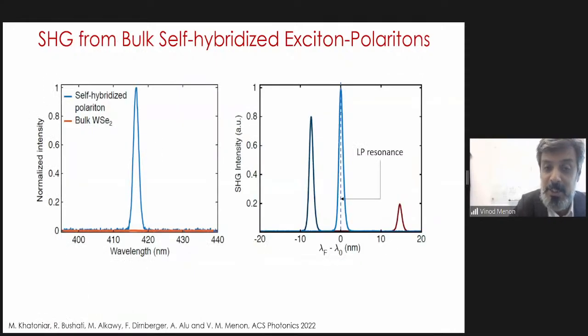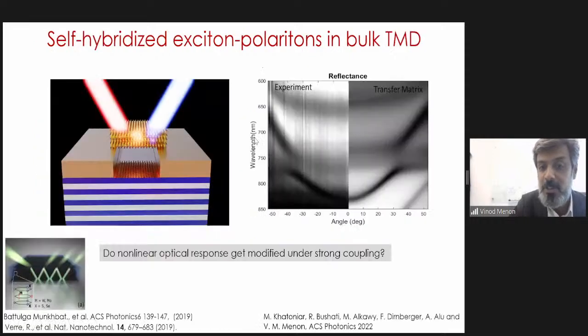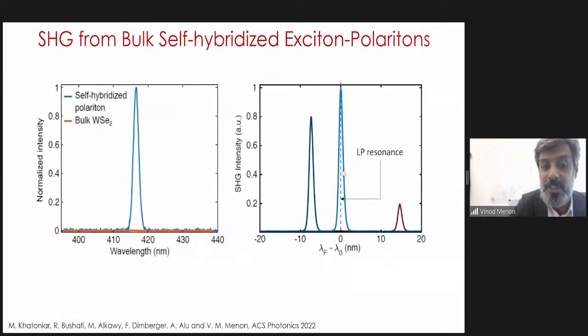But the most intriguing aspect of this structure was we found that if I just took this bulk material of some random thickness and you did second harmonic generation, there's no signal, barely anything in this signal. But then I go to this Polariton system and then I pump here. So it's around 800 nanometers wavelength. And I suddenly get a lot of second harmonic signal. Okay. And so a non-existent second harmonic signal suddenly becomes existent, and it's actually several orders of magnitude higher than what the bulk material does. And also you could tune it depending on whether you're in resonance with the Polariton or not.